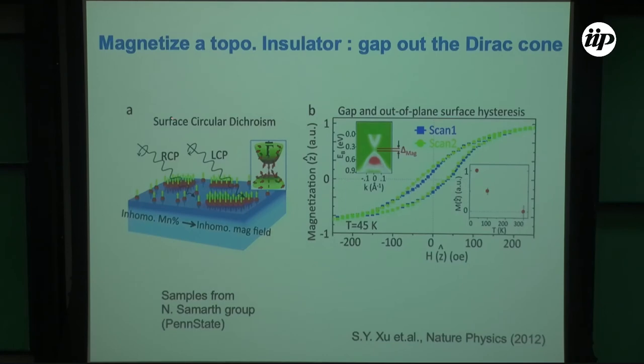So as I said, one thing we do, we can dope in the bulk or on the surface, and then we can look at the dichroic signal and look at the magnetization. And if there is a hysteresis in the magnetization signal, and if this hysteresis is correlated with the observation of a spectral weight suppression or gap, then we believe that we are seeing a magnetic topological insulator. Okay. So of course, the idea of the gap is that the crossing was protected by time reversal, since magnetic impurities break time reversal, so the Dirac crossing is destroyed and you open a gap.